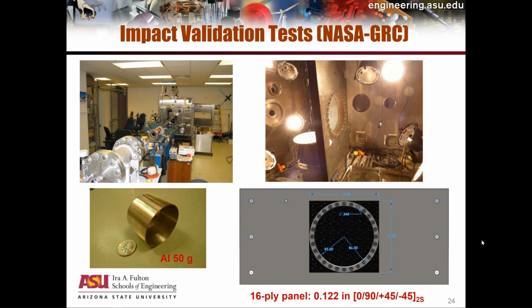So in this case, the projectile is different. It's an aluminum piece, roughly with a mass of 50 grams. So this is the hollow aluminum piece that hits a 12-inch by 12-inch composite panel. And in this particular case, we have taken the T800 F3900 composite, 16 plies in a 0/90/±45 configuration. So the total panel thickness is roughly 0.122 inches.